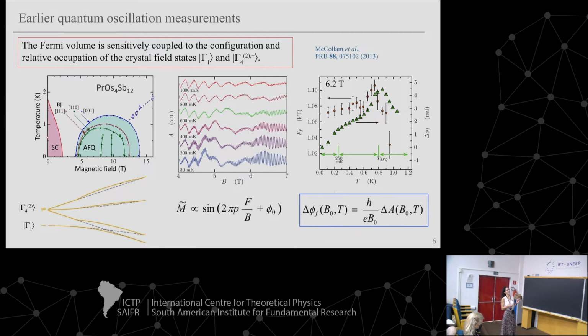This work was done a long time ago, and the story I just want to tell you is that if we think about the magnetization, the oscillatory part of the magnetization for the de Haas-van Alphen effect is 2 pi times, this is just a harmonic number. This is the frequency of the quantum oscillation. So here you've got magnetic susceptibility versus magnetic field, and these are very nice de Haas-van Alphen oscillations that we could see.